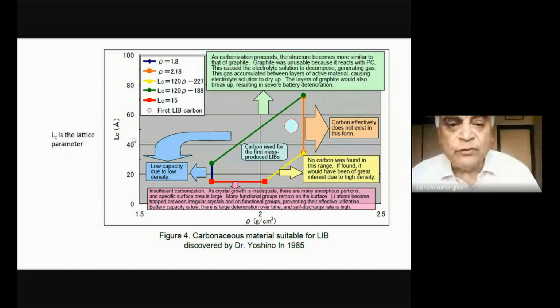Yoshino, what he did was, he stuck to carbon, and he started playing with different types of carbon. All kinds of carbon he started making. And in particular, he started varying the density of the carbon. Okay? And so you can see this is the density axis, and this is known as the lattice parameter. Don't worry about what it is. Okay, but what is interesting is that ultimately he was able to come up with a carbon at a particular density, which really was wonderful, in the sense that it did not get attacked by the electrolyte, by the solvents in the electrolyte. Okay, so I'll just read out what it says here.